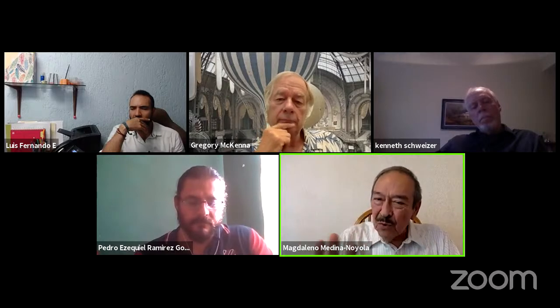Now, why am I saying this? Because much of the questions and much of the discussion has to do with highly packed glasses. And I was going to ask you, Greg, because these solutions near the spinodal are a spinodal decomposition that is arrested by the glass transition, and that is predicted by your non-equilibrium theory. And that corresponds to many materials, gels and porous glasses and so on. But then how much would this discussion today change if we were to move from this highly packed regime, where mostly repulsive interactions dominate the dynamics, the caging effects and so on, when you start to see the effects of attractions?